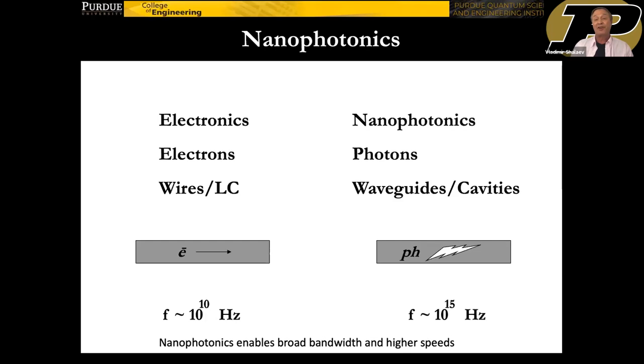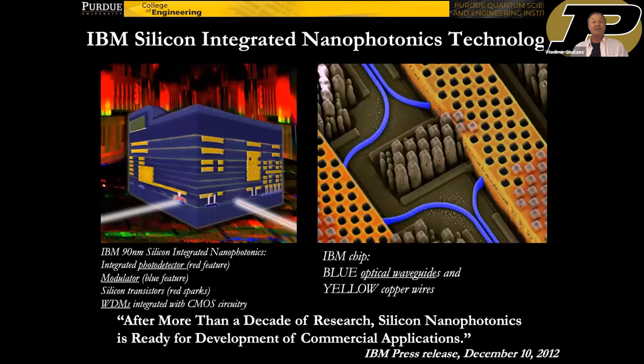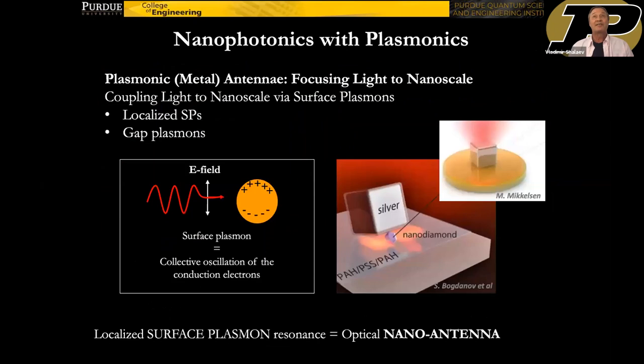In that regard, it's not surprising that computers are starting to use more and more optical elements, such as integrated photodetectors, modulators, and wavelength division multiplexers integrated with CMOS circuitry, and of course, lots of optical waveguides. That's the tendency to place as many optical elements as possible to eventually process information faster. However, when you bring optical elements into your computer, you're still diffraction limited, which means that the size of optical elements is roughly 100 nanometers or several hundred nanometers. So they're still by far larger than the size of electronic elements.